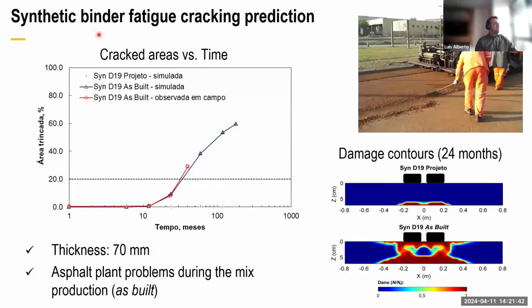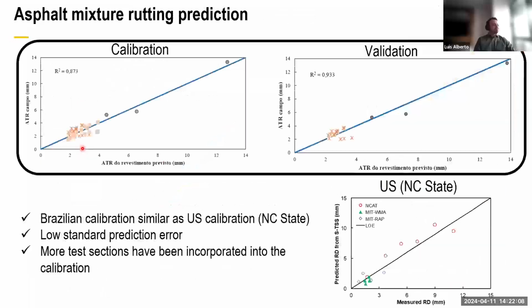This is a synthetic binder, and it's not an asphalt material. We use the same experimental protocol, the same framework, and you see here the as-built property allows us to make this prediction in blue, and the field observed one agrees with the predicted one. So even having a different material, we could make a very nice prediction.